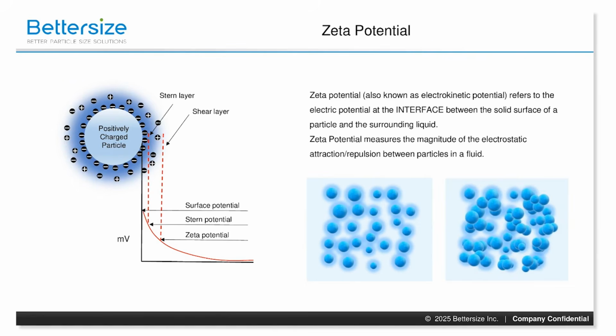High zeta potential means strong repulsion between particles, like common magnetic poles, which helps prevent agglomeration and ensures stable dispersion. It's a critical parameter for understanding and controlling the stability of colloidal suspensions, such as those found in inks, paints, and coatings. There are many factors that affect zeta potential, including pH of the suspension, the ionic strength of the solution, the type of electrolyte ions, the temperature, which can affect the viscosity and dielectric constant of the medium, as well as the diffusion and mobility of the ions in the suspension.